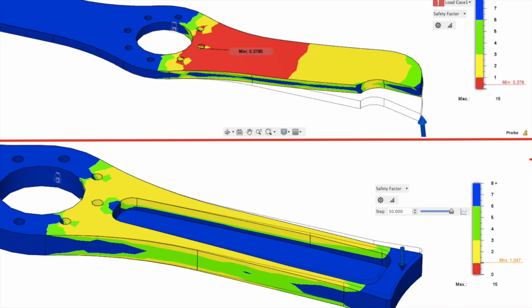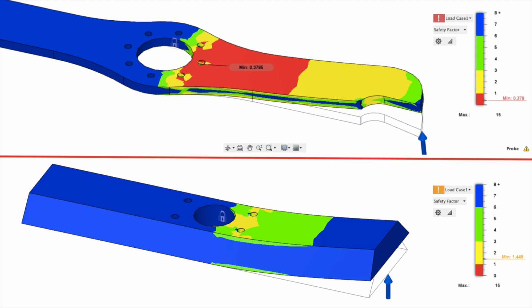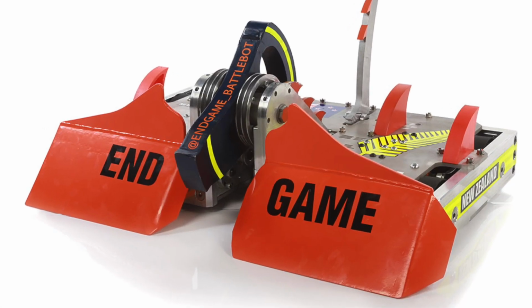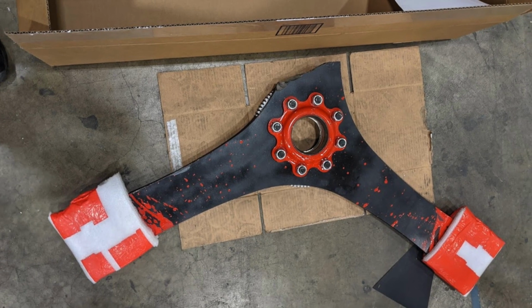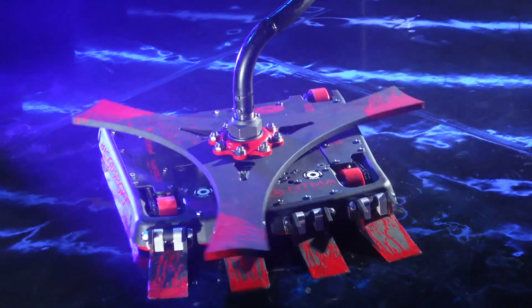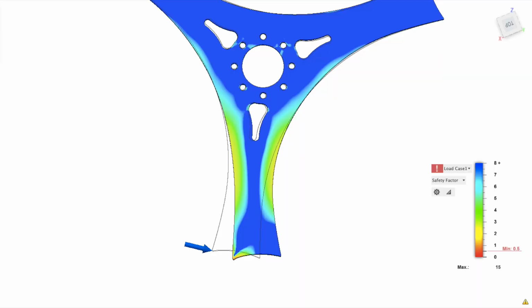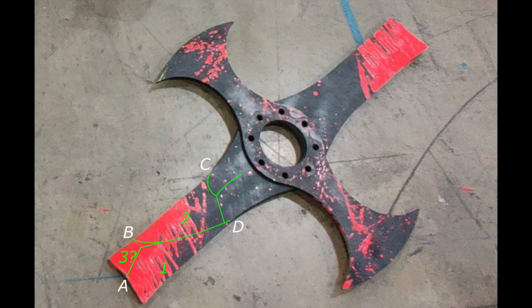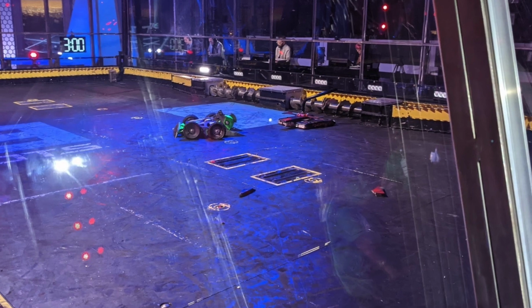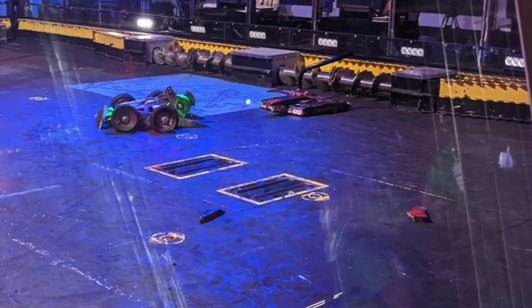Taking a vertical hit to the end of a long bar like ours is probably the hardest problem that we face as a horizontal spinner in the age of Bite Force and Endgame. After the tri-bar broke last year, the adjustment was pretty easy. Switch to the tougher AR-500 steel and shore up the geometry a little to keep it from bending. Designing a replacement for the THICC Bar, however, is a little more difficult, since it was simply not strong enough to take a hit from Lockjaw.